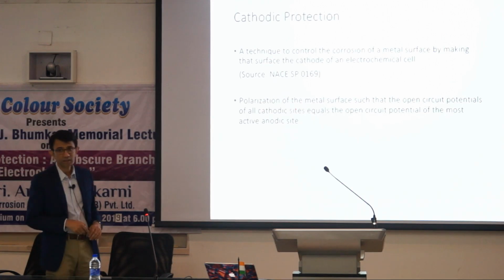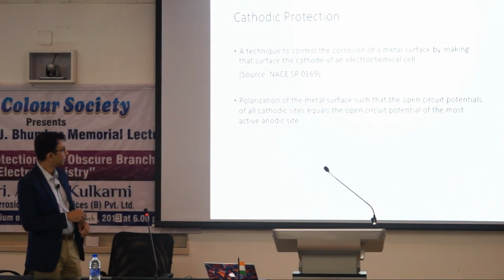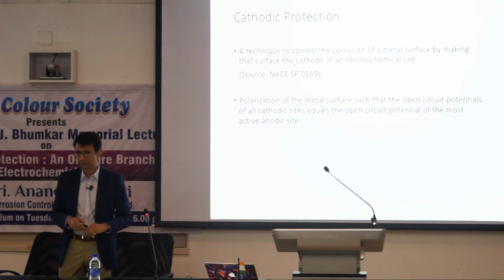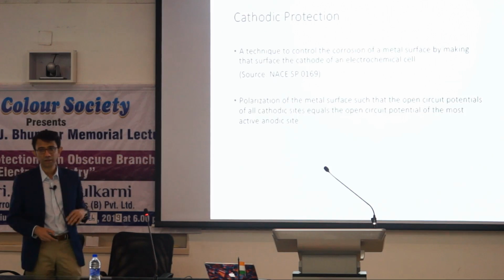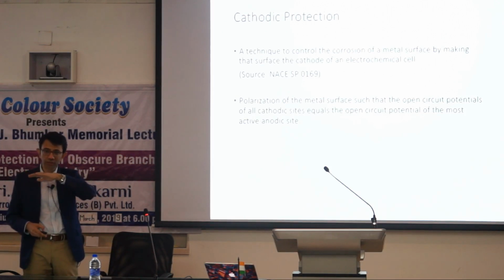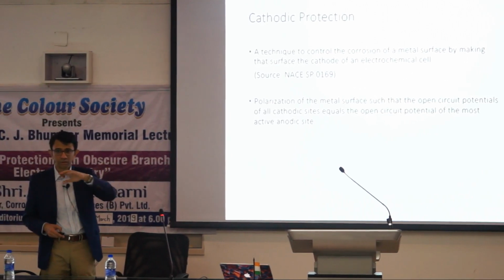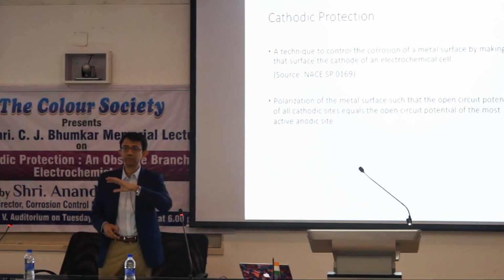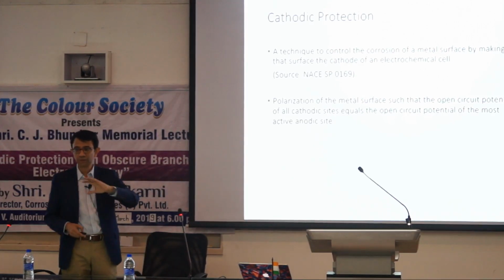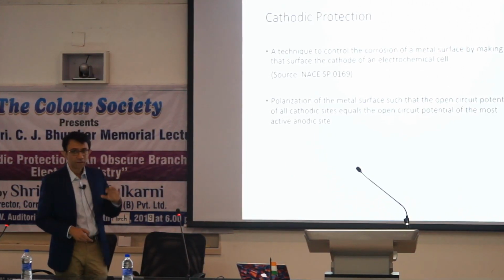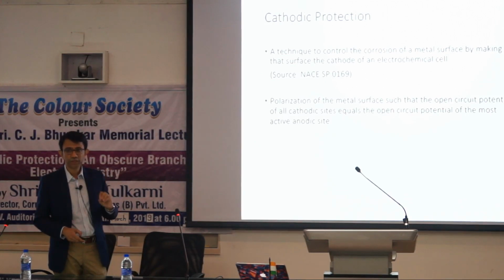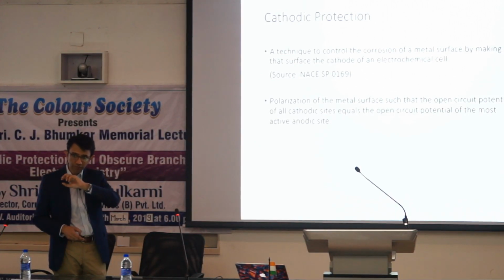This is a more technically accurate definition, which simply says that if you're able to polarize all the cathodic sites, because when you look at a structure like a pipeline, it is the same metal. So what is it that causes cathodes and anodes on the same metal? We already saw some time back a differential cell schematic where we saw that when the soil is non-homogeneous, it may be different resistivities, it may be different salts in the soil, it may be different chemistry, different pH. The result of this heterogeneity of the soil causes a difference in potentials along the pipeline.